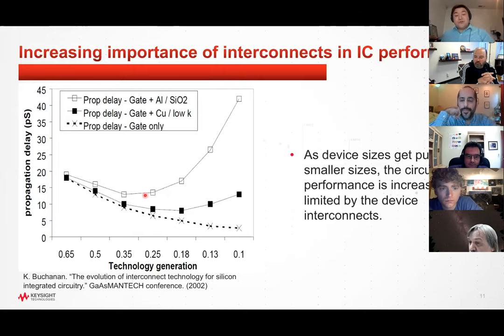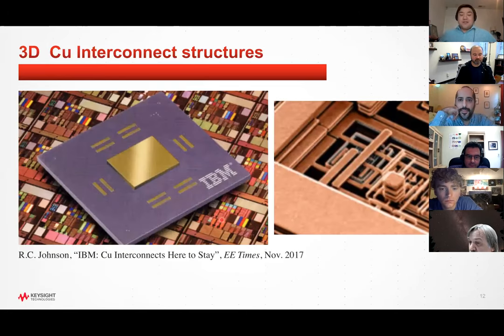And in earlier circuits, the material historically used was aluminum, but you can see that by switching to copper, you're able to get significantly better performance, primarily due to, one, the type of processing we're able to do with copper, but also better electrical conductivity is one of the main things. And so copper interconnects are actually not a new technology. IBM first pioneered this in '97. So this is one of the first chips that they released that used copper interconnects. And here's a photo of what some of those structures look like if you remove everything else and just leave behind the copper. So these are the kinds of things that I got to work on.